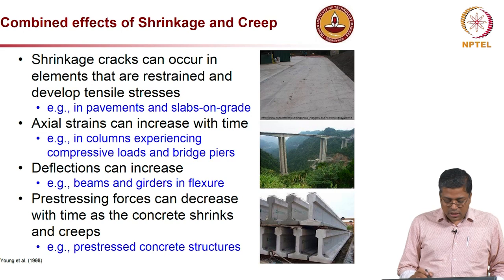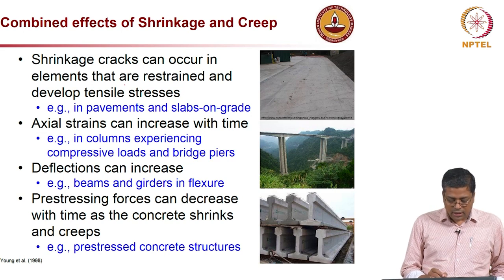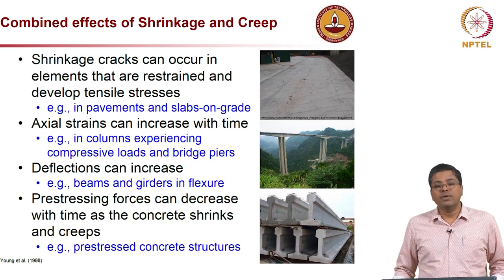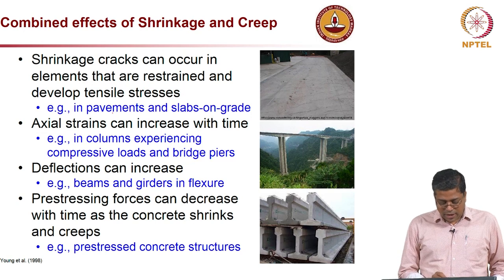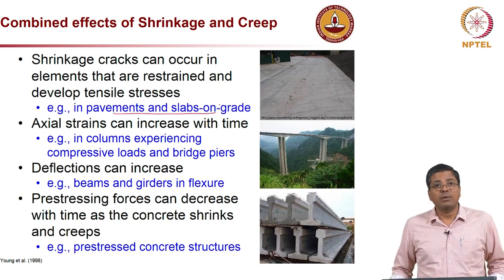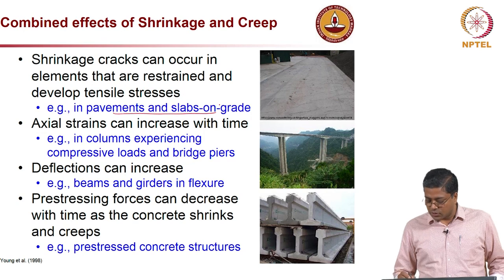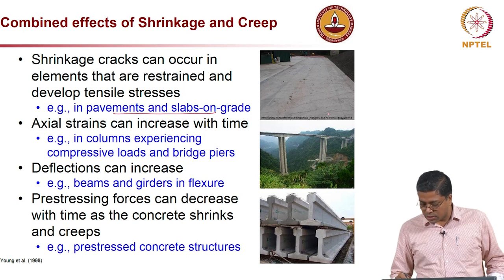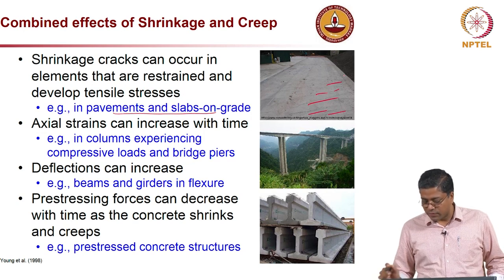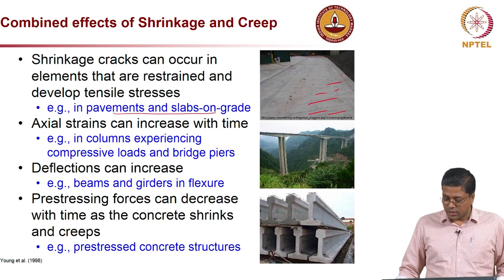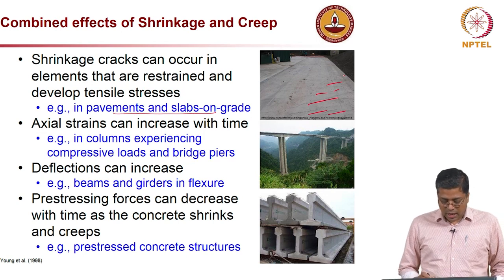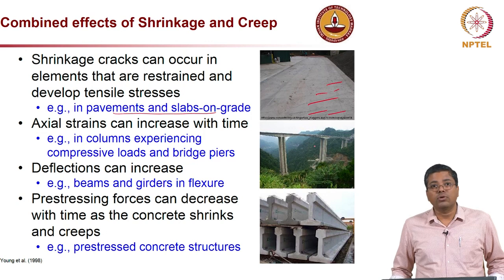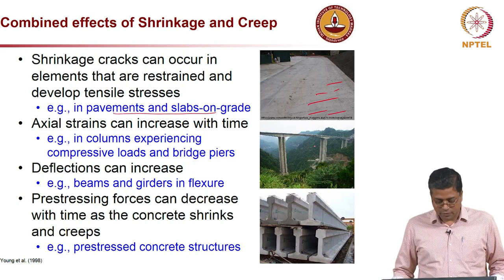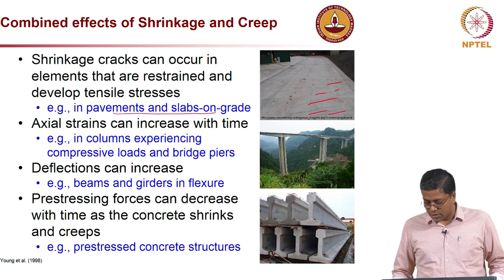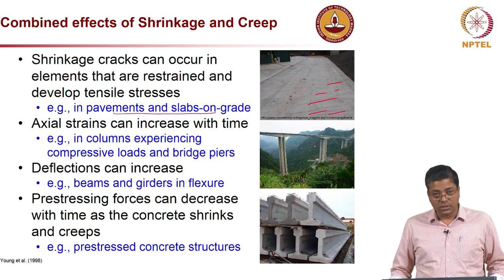Now, shrinkage can occur in elements that are restrained and develop tensile stresses. One example is pavements and slabs on grade. As you can see in this picture, you have a lot of parallel cracks, which are essentially shrinkage cracks. And in the second photograph, you see a very large bridge with very tall piers and long span girders.